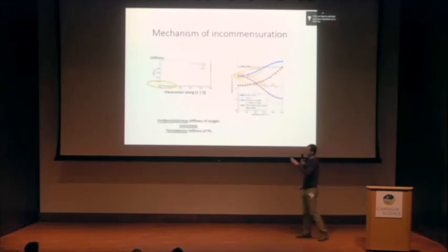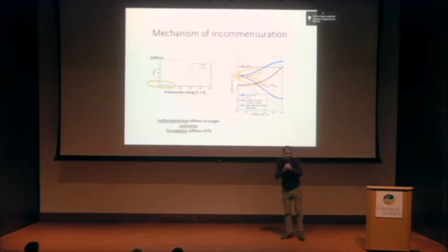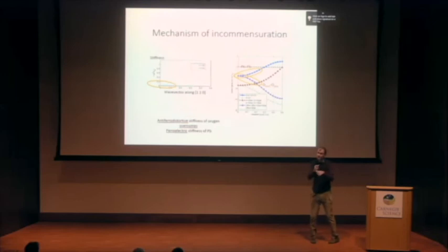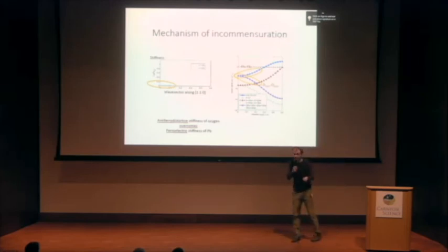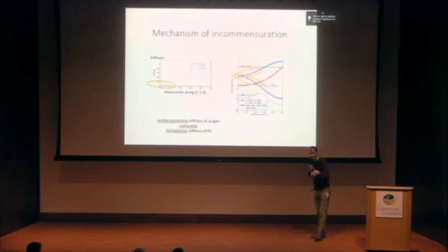First, we answer why it goes down. There is a competition between lead sublattice and oxygen sublattice. Lead sublattice wants to have positive stiffness as ferroelectrics have. But the oxygen sublattice wants to have antiferrodistortive stiffness. And they are coupled by electric fields that they exert on each other. And if the polarizability of oxygen subsystem, the relevant components of that polarizability, are large, then it overcomes the tendency to ferroelectric instability, and the initial stiffness dispersion is negative.